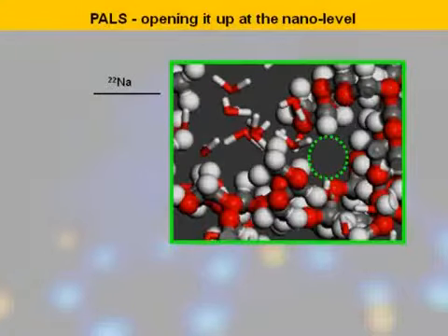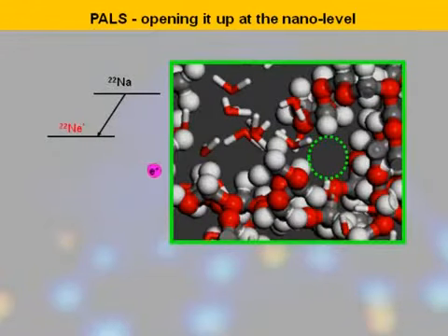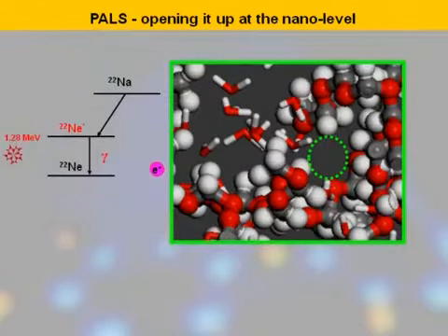In positron annihilation experiments, a positron is injected into a material and we measure the length of time until it annihilates with one of the material's electrons, producing gamma rays. Sodium-22 is used as a source of positrons since during its decay, a prompt gamma ray is emitted simultaneously with the positron. In molecular materials, a substantial fraction of the injected positrons form positronium.